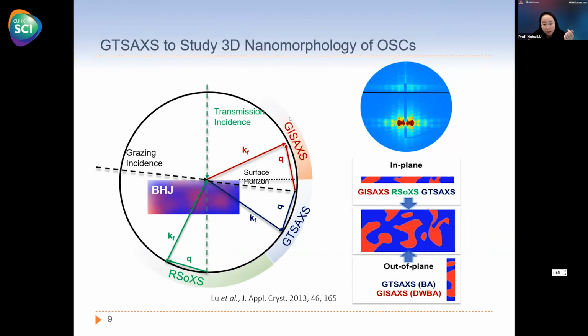So here in convention, we are using GISAXS, which is collecting the scattering signal above the surface horizon of the sample. However, this technique theoretically can also get the vertical nano morphology, but there is the surface enhancement peak called the Yoneda peak that shadows the vertical structure here. So we are trying to make use of the scattering signal that escapes from the front edge of the sample, which is called the grazing incidence transmission signal, to get rid of this Yoneda peak and get the clear vertical nanostructure.